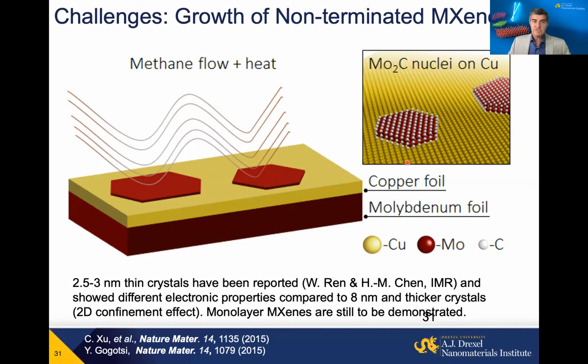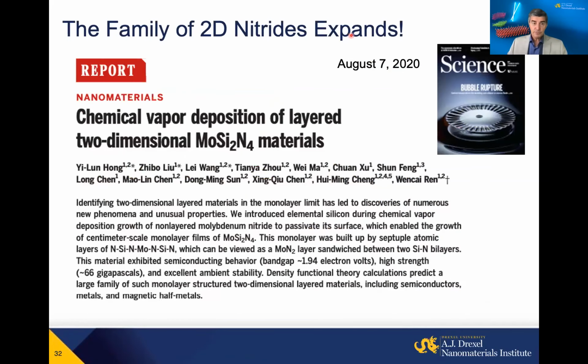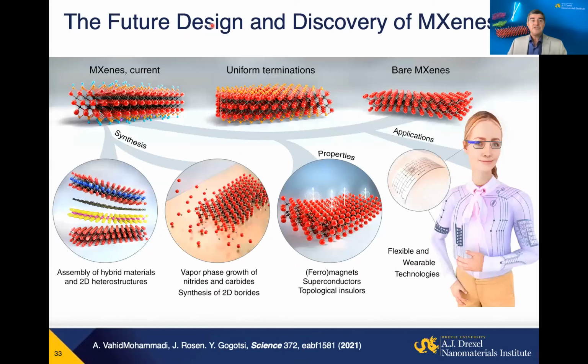There have been several papers producing very thin layers, for example, like Mo2C, but those are not monolayers here. This is Ren and Huimin Chen's work from IMR here. Trying to produce MXenes, they actually discovered a new type of two-dimensional nitride, a type of molybdenum silicide nitride material. This paper was in Science last summer here. But clearly, CVD-PVD growth is the next frontier as well here. And of course, achieving uniform termination, controlling properties through chemistry of these materials, exploring properties of bare MXenes, which will be like electride bonded monolayers, creating two-dimensional ferromagnets, and many, many others are still targets that need to be explored.